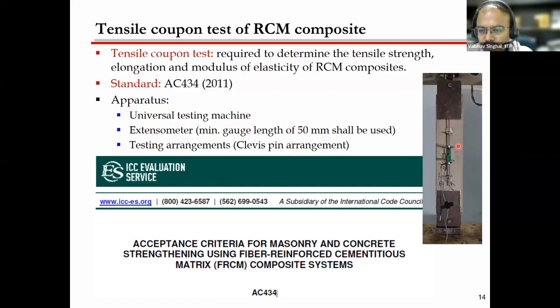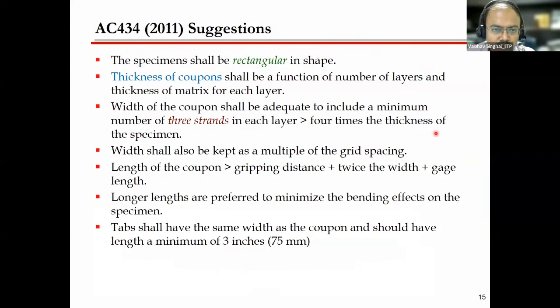Here you can see this gray color, which is the cementitious matrix. Now, one can follow this code, AC434, which was published in 2011. This can be used for the material characterization for the tension coupon. Let me give you some of the criteria or suggestions given by the code. It says that the shape of the specimen should be rectangular, and the width should be at least equal to that which can accommodate 3 strands, the 3 reinforcing wires or 3 fabric layers, and it should be at least 4 times the